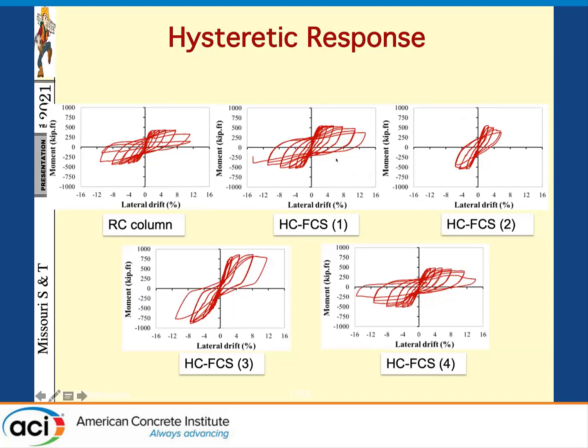This is very much similar to reinforced concrete. I mean, if you see this one, you probably cannot tell if this is a reinforced concrete or the hollow core column. So it behaves very much similar to reinforced concrete. Very nice plateau. The others have different modes of failure. Here, the one with the FRP early rupture. To the bottom over there, this is the pull out, and you see the slip that occurred, the pinching that occurred in the hysteretic loops. This is also a well-designed column.